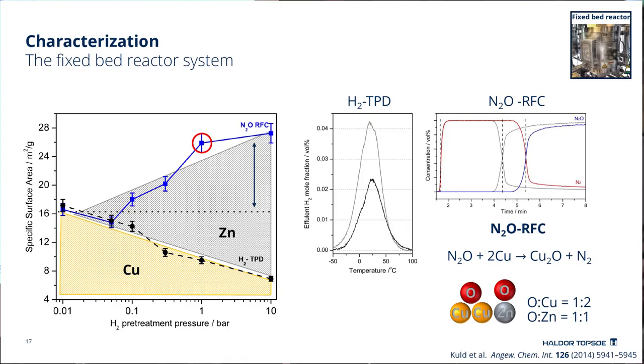So this is quite peculiar. It's the same catalyst, and it's not time on stream effects because the catalyst is reloaded in between all the experiments. So what is really going on here? If we, on the other hand, look with the nitrous oxide, we see something completely different, or actually the opposite phenomenon. Initially, we see a front duration of around 4.5 minutes. And if we go to the pure hydrogen case, or one bar of hydrogen here, we see that this front duration has actually extended.